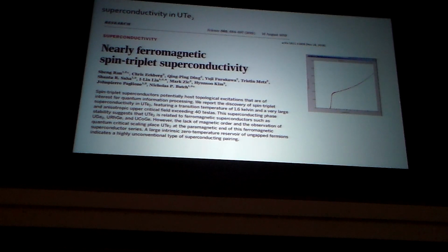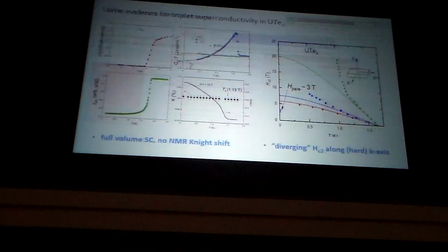But the TC of this stuff is around 1.6 Kelvin. And this was discovered about 5 years ago, and this has generated a lot of excitement. So there are a lot of papers now, a lot of experiments done on this uranium telluride (UTe2) material, and there are a lot of very interesting properties about it. The thing that might be relevant to topological behavior, topological superconductivity, is something called chiral, which means that time reversal symmetry is broken in the superconductor. That is actually important for using it in quantum computation.